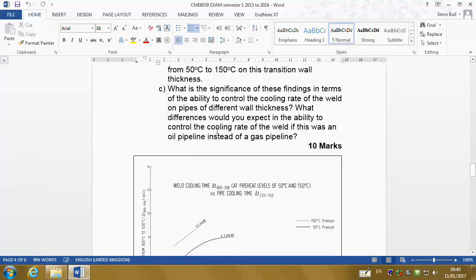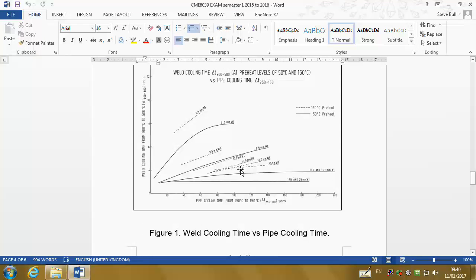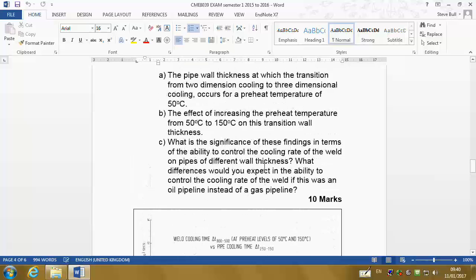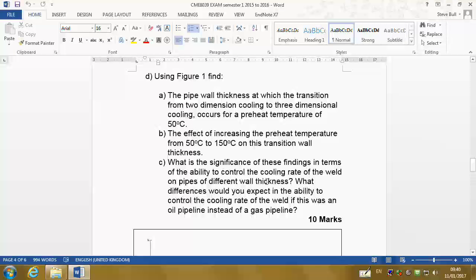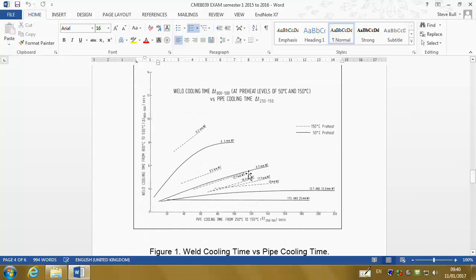There's a slight difference between temperatures, so you compare the solid curves to the dotted curves. That's okay. And what's the significance of these findings in terms of the ability to control the cooling rate of the welds of pipes of different thickness? How do you control the cooling rate? You look at that diagram. You've got different cooling rates here and here. What you'd like is something where you've got a very easy relationship. So if you've got a nice straight line, like here, you control the cooling rate basically by the thickness that you've got.